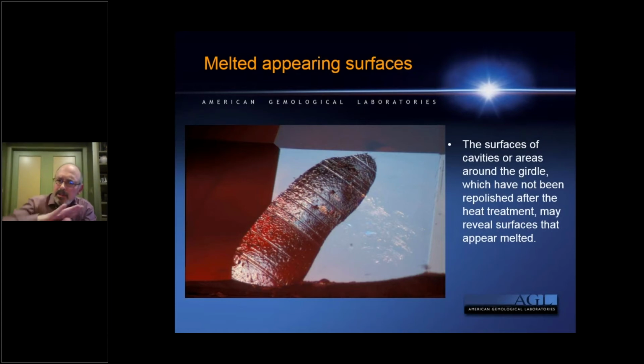They might have a melted or slightly molten appearance. You might have little droplets of contamination from the bricks of the oven as they degrade. They'll adhere themselves to the surface of the stone. And so there are little practical things that you can look for here as well to help recognize whether a stone has been heated or not.